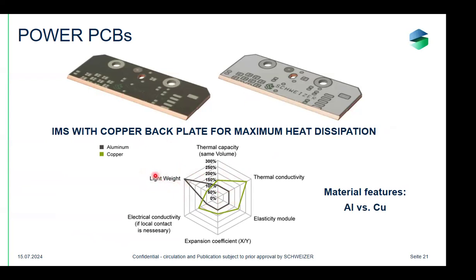So aluminum-backed IMS boards are lighter, but the thermal conductivity of a copper-backed IMS board is higher. We also have a higher Young's modulus. The CTE is lower, and this is important for a better reliability of the assembled components because it leads less stress into the solder joints if you do a soldering on the top. And also the electrical conductivity is better if you need to have a local contact.